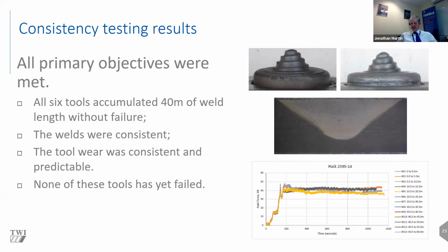So all these 6 tools accumulated the 40 meters without failure. The welds were consistent. We didn't see any flaws or defects in the weld that caused us any concern. The tool wear was consistent, and none of these tools failed during this testing regime. So I'd like to hand over to Santonu now to show you some of the results in terms of the scanning. And so Santonu, I'll hand it over to you.